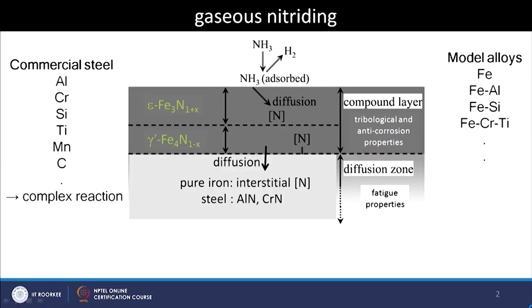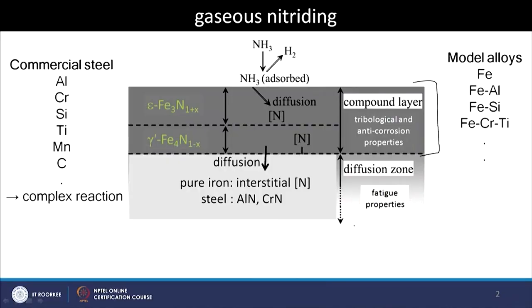This slide shows the schematic microstructure we discussed in the last class. To cover it quickly: we have an outer layer called the compound layer, often called the white layer, because when you do metallographic preparation of nitrided specimen cross-sections, etch with nital, and view under a light microscope, the iron nitrides appear white — they do not get etched and simply reflect all the light back. The other layer is the diffusion zone.